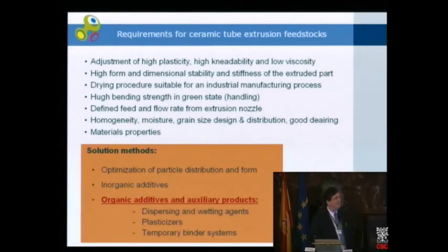Of a high precision tube. And for sure, to produce a tube, you select the extrusion technology. That means you have to develop a performing extrusion feedstock, a compound, to adjust the plasticity and to adjust the viscosity. But what counts at the very end is the form and dimensional stability and the stiffness of the extruded part. And in a second, I will show you the hard facts about the dimensional tolerances of this material.